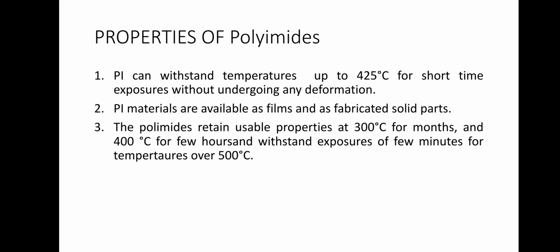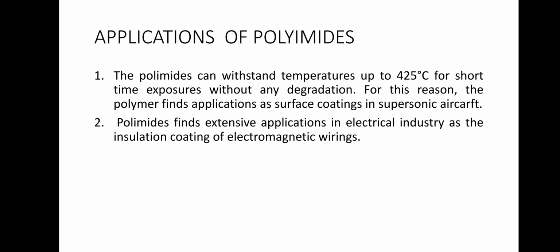deformation. PI materials are available as films and as fabricated solid parts. Polyimides retain useful properties at 300 degrees Celsius for months and 400 degrees Celsius for a few hours, and withstand exposures of a few minutes at temperatures over 500 degrees Celsius, which is similar to metals.